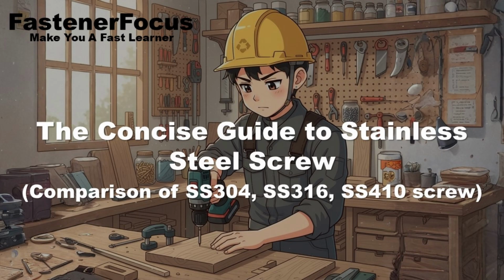That sounds like a guaranteed failure mechanism in coastal environments. So what does molybdenum do specifically to combat these conditions in grade 316? Molybdenum essentially stabilizes the passive film against the direct corrosive action of the chloride ions. It achieves this by being incorporated directly into the chromium oxide film, making the film more tenacious and resistant to breakdown, even under those highly acidic, low-oxygen conditions found inside a crevice. This is why 316 is the marine grade, because it provides a reliable long-term defense against the relentless attack of salt spray, de-icing salts, and chlorine-based chemicals. It's a necessary and, yes, expensive insurance policy for high chloride environments.